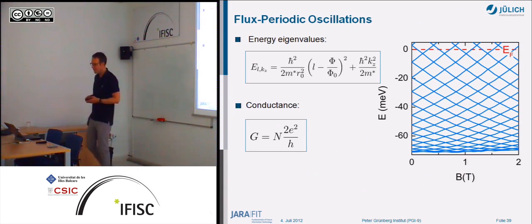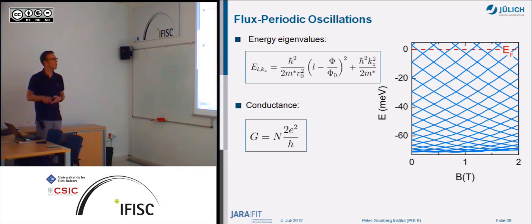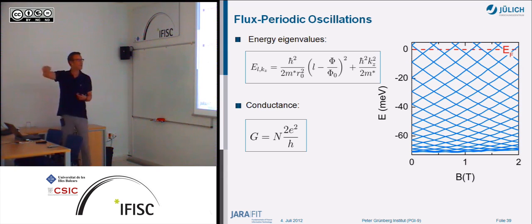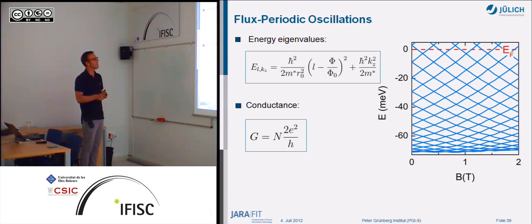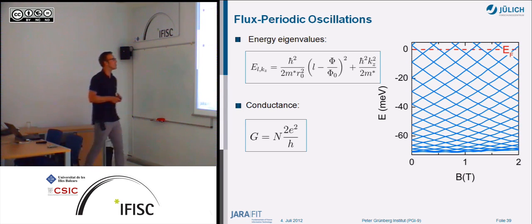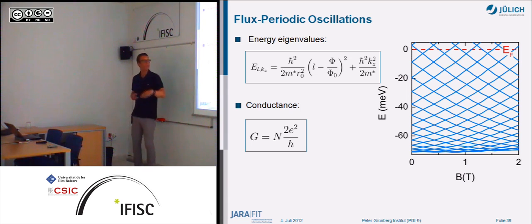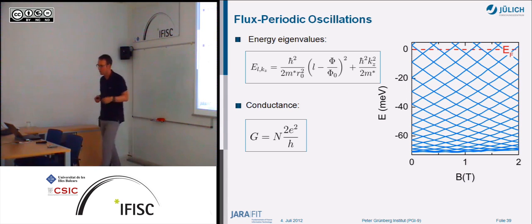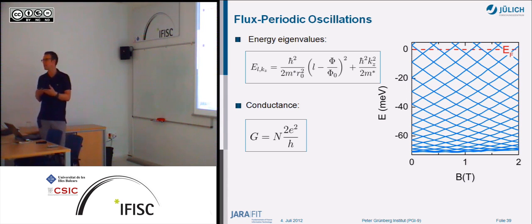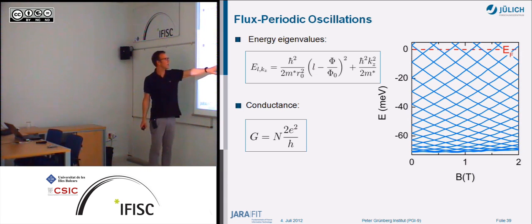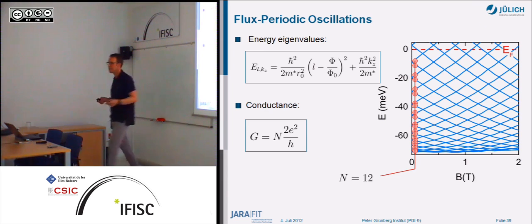And the explanation for that is that you have to look at how many one-dimensional states you have, when the energy values can be written like this. You have these quantized states because of the angular momentum and because of the magnetic field, the flux. That's this here, the flux is here, the angular momentum is here. This gives you this state here, which is flux periodic. So if you look here, the period is one single flux quantum. But of course, you also have the transport along the nanowire, which is this here. So you have one-dimensional states, like in a split-gate quantum point contact. So ideally, the conductance should be just the number of states multiplied with the conductance unit of 2e squared over h, like in a split-gate quantum point contact.